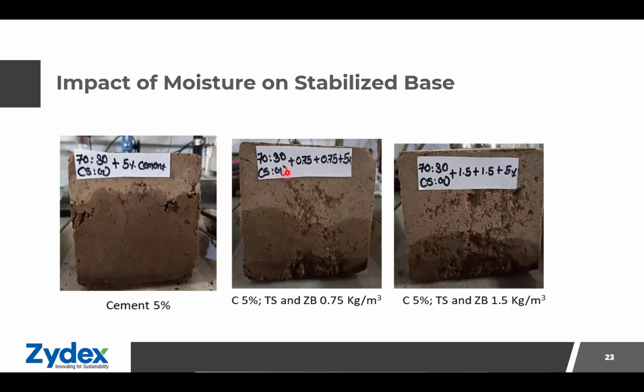And as we add the water repellency additives, that is Terrasil and Zycobond, the water uptake gets reduced as the dosage increases. For this figure, we have a dosage of 0.75 kg per meter cube each of Terrasil and Zycobond. And for the last figure, we have the dosage of 1.5 kg per meter cube. So this is just a visual representation, but what happens to its strength?